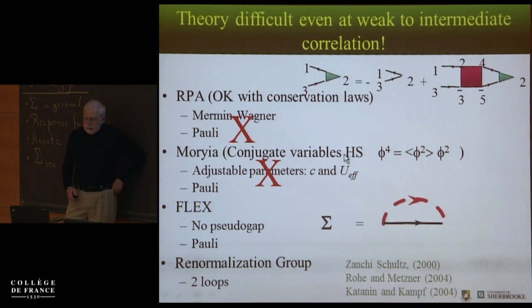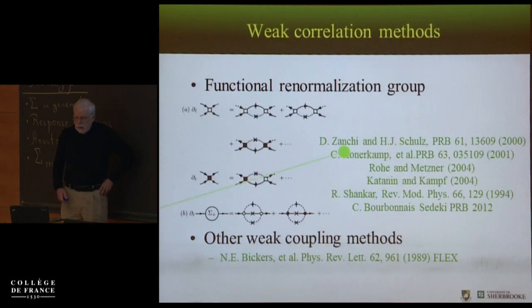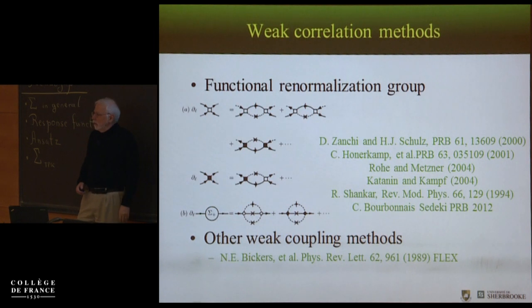The same in the fluctuation exchange approximation, which is like Eliashberg theory, but here you don't have Migdal's theorem, and you're dropping the vertex correction that should really be there. As a consequence, you don't have a pseudogap, and you don't have the Pauli principle. Renormalization group does better. On the other hand, in RG, to get the self-energy, you need to go to two loops. You need to do it functionally, so it's really a big calculation. And also, you lose control of the calculation as soon as you get close to a large antiferromagnetic correlation length, or as soon as you get close to a phase transition.